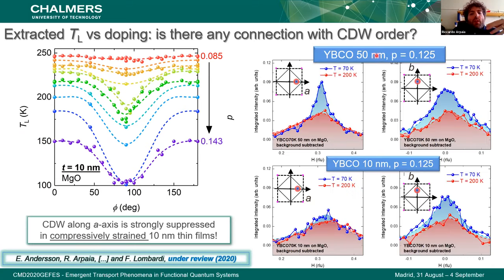In fact, in the 50 nanometer film, what we get is that at high temperature, we only have charge density fluctuation, this very broad peak, and then at low temperature, we get in both directions a peak of charge density wave. But when we go to the 10 nanometer instead, along one axis, we have a presence of charge density wave very similar to the one of the thick film.